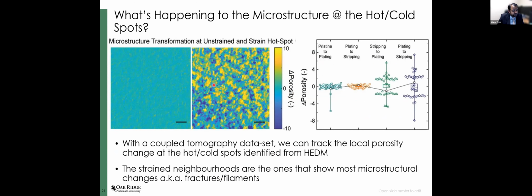However, in the regions where we did see these hotspots, where the maximum and the minimum of the stress were identified, we saw that those local regions show a large change in porosity between the pristine and the failed sample. So this is consistent with the idea that a change in porosity is linked to formation of cracks or potentially formation of filaments within the solid electrolyte. And so this was very interesting to us.